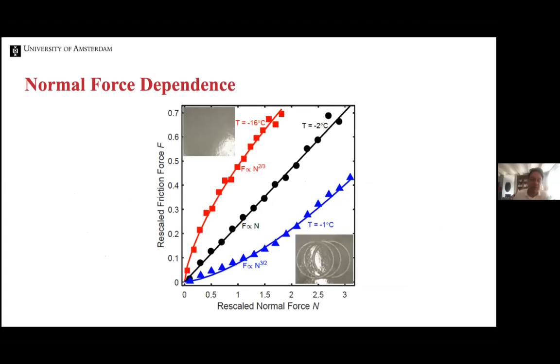What does give a clue about the mechanism is if we look at the Da Vinci plot, if you like. This is the friction force and this is the normal force, and so Da Vinci said that they should be proportional, and they sometimes are, but mostly not. And notably, if you go to temperatures very close to the melting point, you get a dependence that is close to 3/2, which I will explain to you in a second.